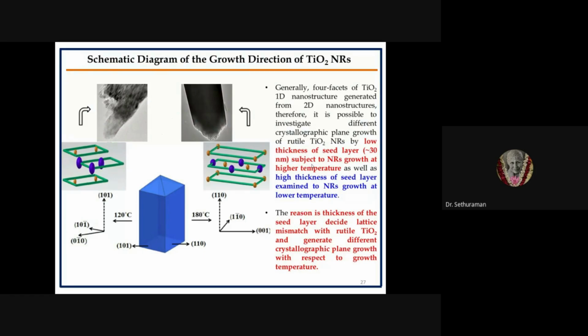From the work, we grew these nanorods at two different temperatures, 120 degrees Celsius and 180 degrees Celsius. From the observations, we found the crystallographic plane growth of rutile TiO2 nanorods depends on the seed layer thickness. A lower thickness seed layer used with the higher nucleation growth temperature gives the 110 crystallographic orientation. The high thickness seed layer with the 120 degrees Celsius growth temperature gives the 101 crystallographic orientation.